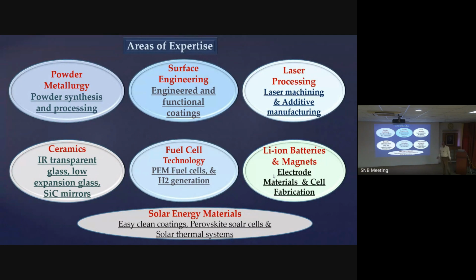And then hydrogen generation is there already, because now we are seeing PEM based electrolysis so that you can get pure hydrogen and oxygen without any mixing, so that you can separately do it on board. And lithium-ion batteries are our stronghold, where we make materials, especially in large scale, which are key, like lithium iron phosphate. And when we make the material, we also validate it at the actual device level. So we have a pilot facility where we can make all form factors, like 18650 and 21700. All these form factors, different sizes of cylindrical cells, are relevant to the automotive battery industry. And that's what we demonstrate.